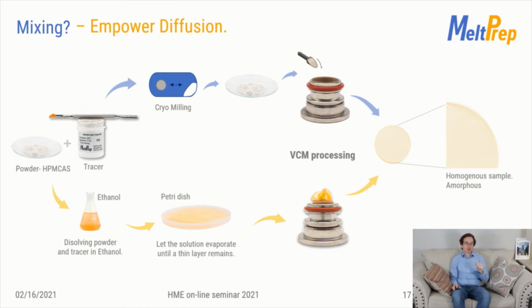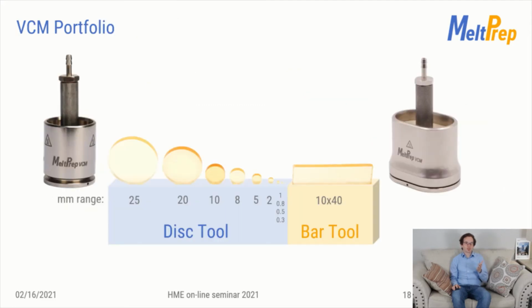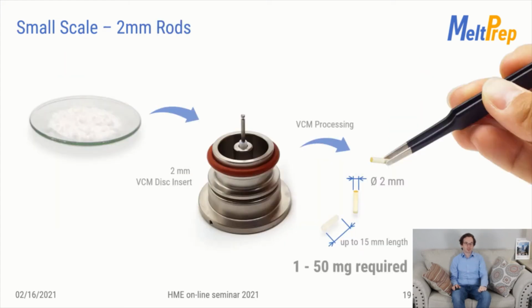One thing I'm very proud of is the small-scale development that we did. I kicked the VCM tool off with a 25 mm disc diameter in 2014. My former colleagues at the RCPE were requesting smaller dimensions for their investigations. So we reduced it down to 5 mm to make it suitable for DSC and later even to 2 mm samples. You can use those small dimensions for the screenings of implants, for example. 1 to 50 milligrams are sufficient to prepare a prototype of such a subcutaneous implant.